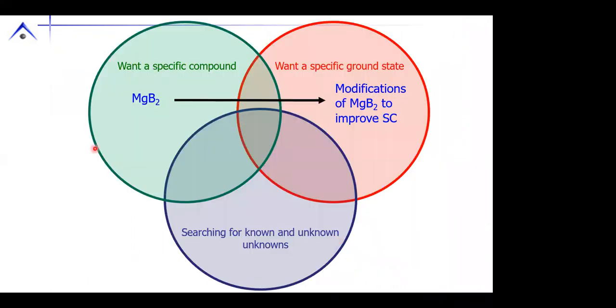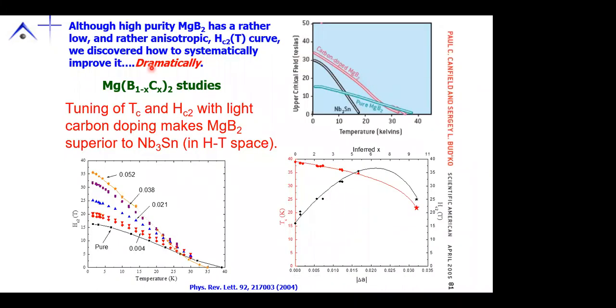Now, with that said, we went from wanting a specific compound to actually very much wanting to see if we could modify or improve superconductivity in MgB2. And the reason we wanted to do that is because niobium-3 tin was the industrial standard for superconductors. David Larbalestier and co-workers eked the last Teslas out of Hc2 here through Herculean efforts. Pure MgB2 has a much higher Tc, but has a very low Hc2. And what we wanted to do was see if we could increase this Hc2.